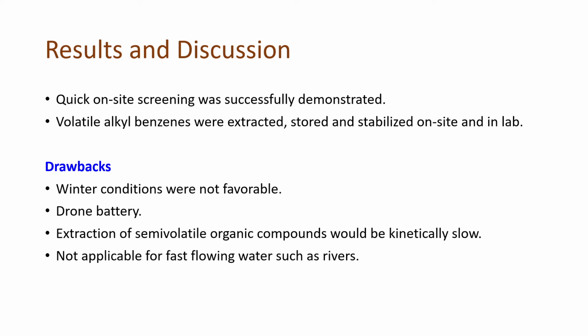Here we can see that quick on-site screening was successfully demonstrated with this method, and some other volatile alkyl benzenes were also extracted and stored, and stabilized for on-site and lab analysis. But there are some drawbacks. The winter conditions were not favorable because they resulted in depletion of the drone battery, and the extraction of some semi-volatile compounds was kinetically very slow because of the winter conditions. This method is also not good for fast-flowing water like rivers. It is usually good for ponds and lakes.